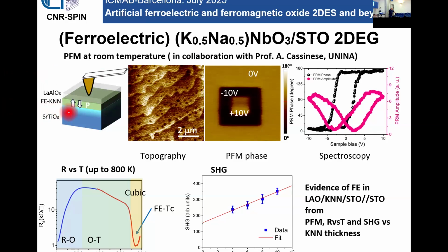Probably all of you know the technique, but it's based essentially on writing or switching locally the polarization of the ferroelectric. If the material is ferroelectric, with the gate voltage you can write these nice patterns. And you can see in this PFM phase image that there is a clear, nice change of 180 degrees of the phase between regions written with a negative voltage and a positive voltage on the tip.